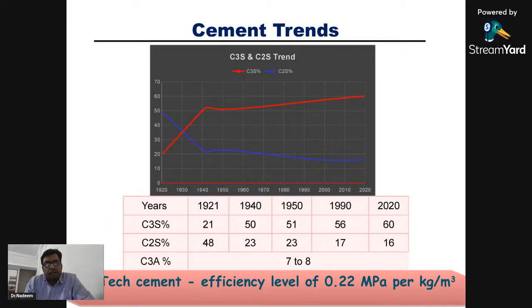But as time progressed and as the need came for high strength or high grade of concrete, all the cement companies started focusing on increasing the percentage of tricalcium silicate. So if you see year-wise, every decade, the percentage of tricalcium silicate in cement increases. Nowadays it's more than 60% tricalcium silicate, which started from 20%, and dicalcium silicate, which started in say 1920 from 50%, has now reached almost 15 to 17%. On one side we are getting very good strength from the cement. Nowadays, good OPC is giving a strength of say 60, 65, or 70 plus MPa.